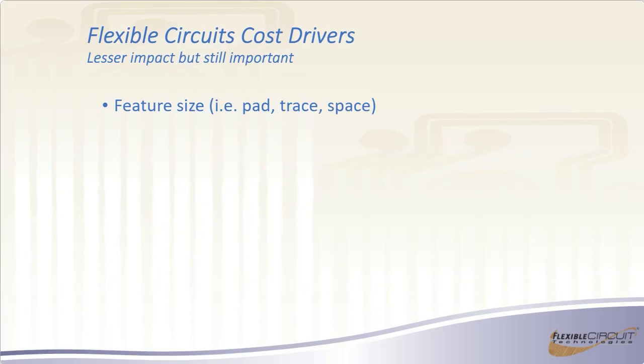Feature size, obviously, as things get smaller, the odds of having stray flaws increase. So whether it's pads, traces, or spaces, bigger is typically better. There are industry standards: while everyone can go down to 25 microns or less, no one's really doing it without a pretty good impact on yield. Typically 75 micron trace and space is the stepping point where you start really having an impact on yields.